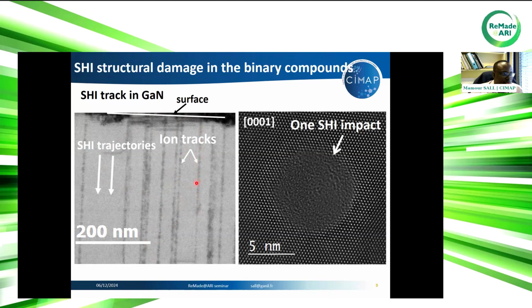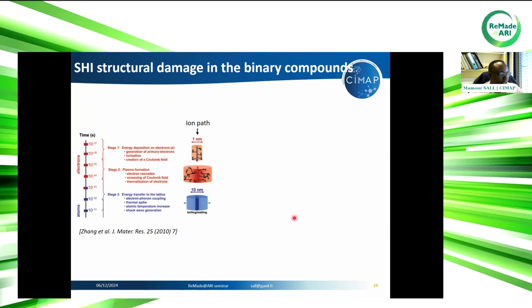In the image on the right-hand side, this is what we call a plan view TEM image. In this case, we observe the sample from the surface. So we can see each ion impact from the surface. In this example, you can see that the track is completely amorphous with a diameter of around 5 nanometers. So each ion will create in the material an amorphous cylinder. From this, we could think that gallium nitride is very sensitive to swift heavy ion radiation, but this is not exactly the case, and I will try to explain why in the next slide.